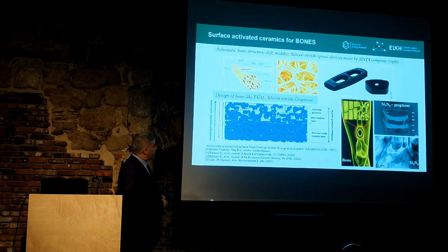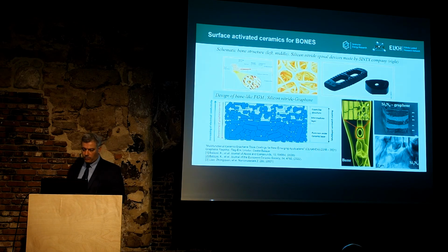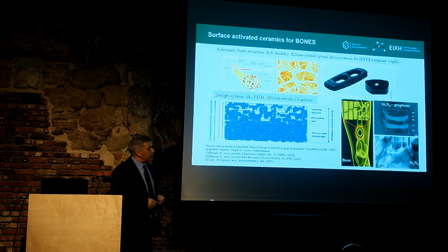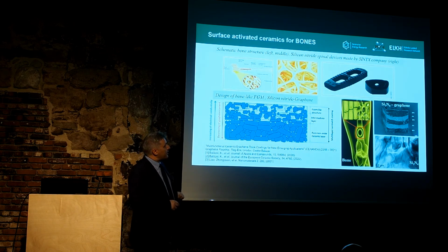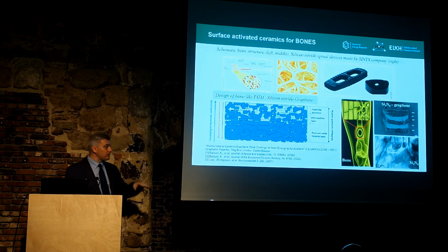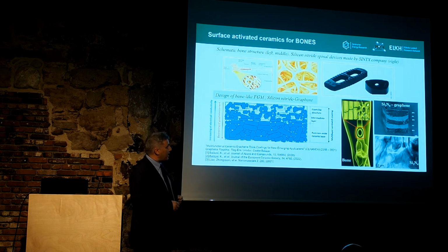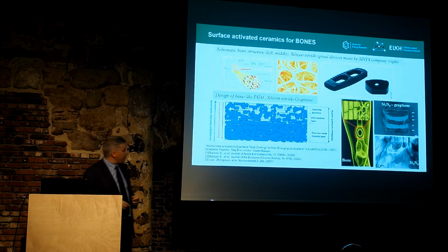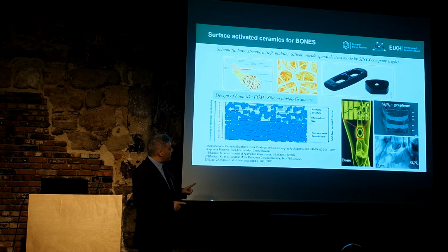In our research, we also concentrated on bone structure, so we have cortical dense bone and then trabecular porous bone. We can provide this structure by using silicon nitride. Actually, we have a laboratory that has been working on silicon nitride for more than 30 years, but we were concentrating on other applications at that time. We know that after alumina and zirconia, which dentists happily use, zirconia-toughened alumina and alumina-toughened zirconia are in widespread use, but nowadays silicon nitride is becoming more and more fashionable. As a spinal device, you can see that the American company Amedica is producing it. We fought in a European project, Graphene Flagship or FLAG-ERA, to make the same bone structure from silicon nitride.